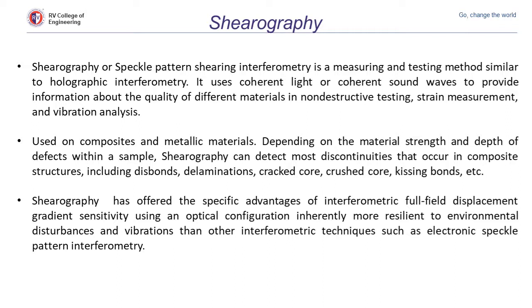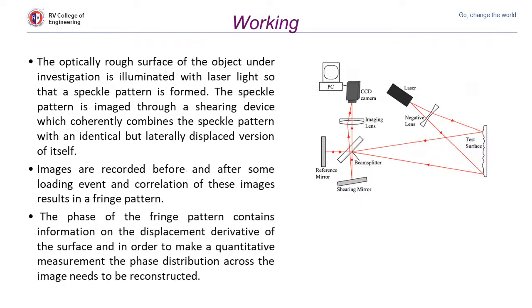The technique is called electronic speckle pattern interferometry. The basic difference between holography and shearography is that holography is proportional to the actual displacement of the surface due to the external load applied to the structure, whereas the shearography fringes are related to the slope changes of the surface.